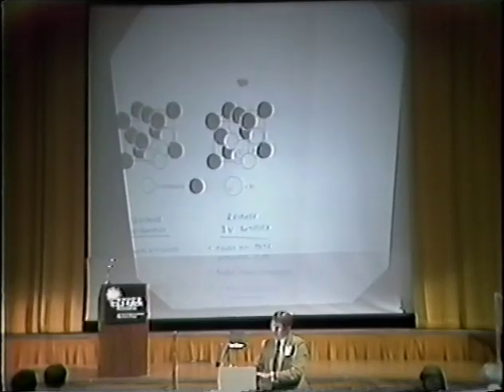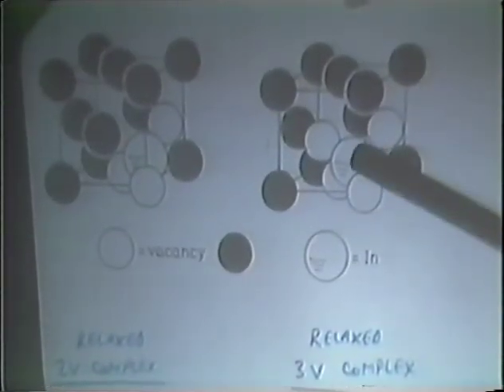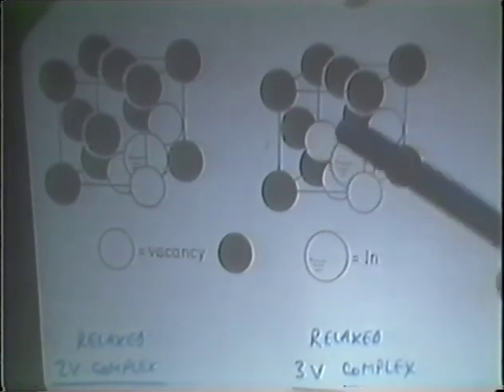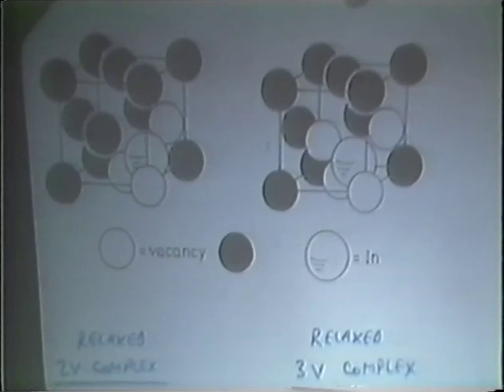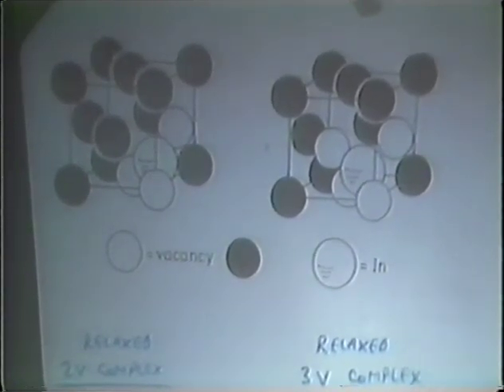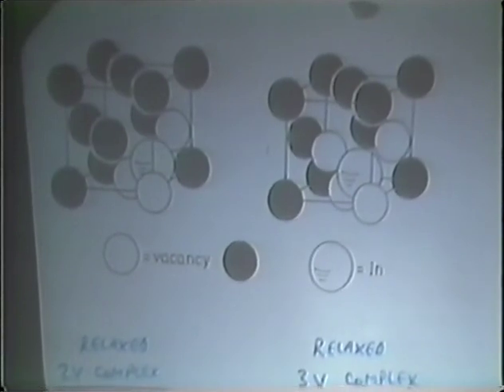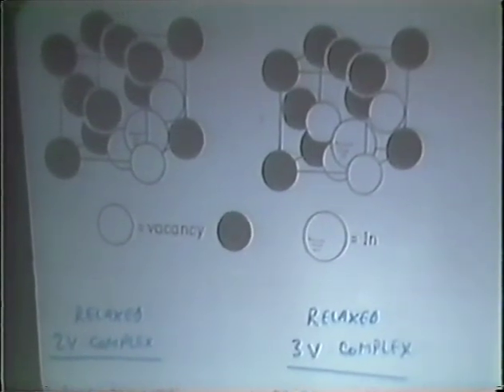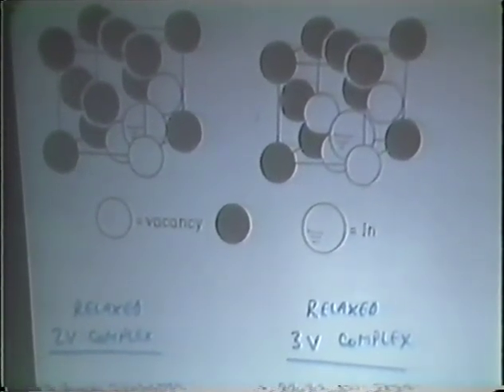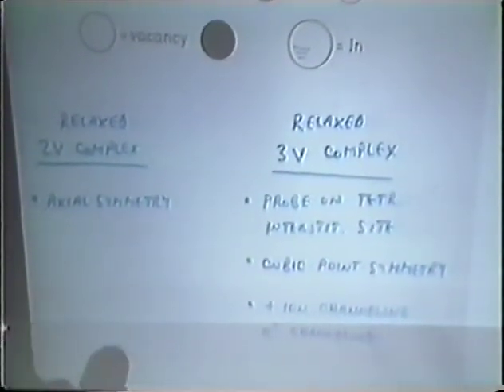Now, the nature of that specific defect complex, which I just showed you a signal for, the low frequency one, is the following. As shown on the right-hand side of the figure, it involves an indium probe atom sitting at the middle of a tetrahedron of vacancies in the FCC lattice. We know this for 2 reasons. From the PAC signal, we know that the point symmetry is cubic, and also indium atoms have been observed to move to tetrahedral interstitial locations at the same temperature that we observe the formation of that signal via PAC, by positive ion channeling and also by conversion electron channeling.